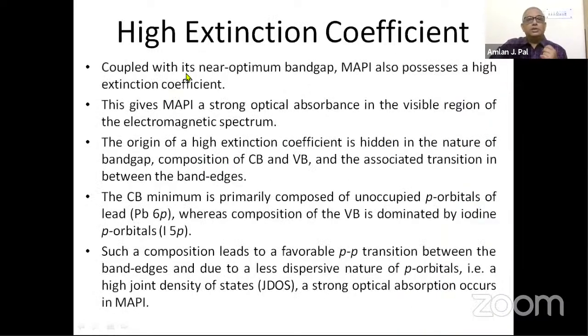And another important factor is the high extinction coefficient, because optical absorption depends, apart from the band gap, also on the extinction coefficient. And because of this nature of the conduction band and the valence band, it possesses a very high extinction coefficient, and this basically occurs because of the p-p transition between the band edges.